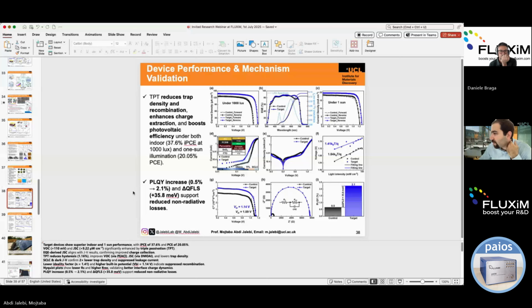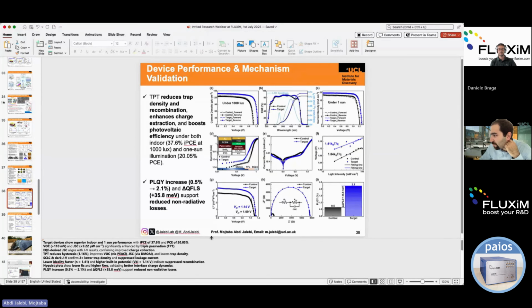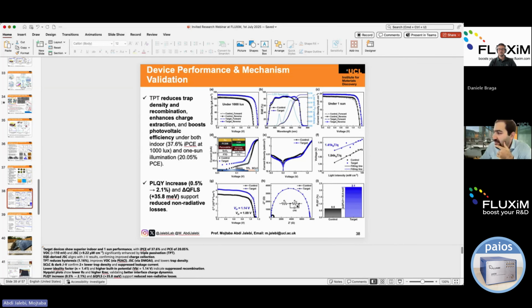All right. That's a very good question. Thanks very much. From the impedance, what we get is mostly to extract the recombination resistance as well as the series resistance. What we found here is that when we have this TPT or triple passivation approach, we maximize the recombination resistance. So in total, we have less non-radiative losses, and the recombination resistance is higher. That means we have preferred pathways for the charges to reach the contacts with minimum non-radiative recombination. On the other hand, the series resistance is reduced quite significantly, so we have less resistance for the charges to reach the contacts. On the migration side, we mostly refer it to the bandgap stability.